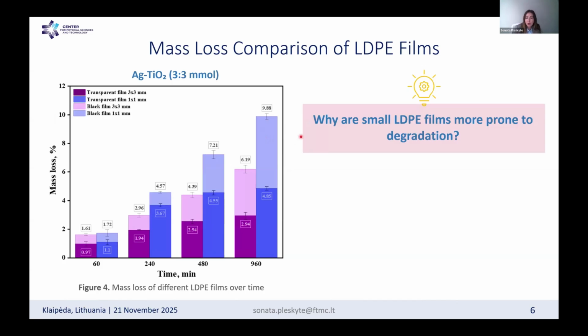So this means that a higher surface area to volume ratio maximizes the interaction with the photocatalyst and also with reactive oxygen species. At the same time, it also enhances the light exposure. And what was interesting is that during the experimental work, we also noticed that smaller LDPE films were more evenly distributed in the reaction solution compared to larger LDPE films, since larger LDPE films tended to block each other's surface and overlap each other, and of course that reduces the possible active sites for reaction with reactive oxygen species and also the catalyst.